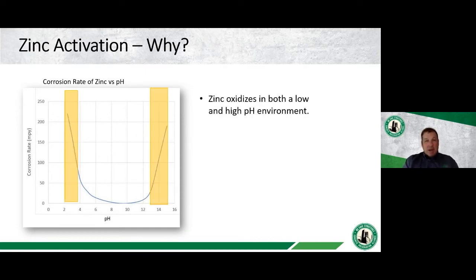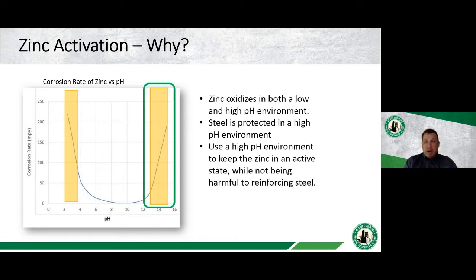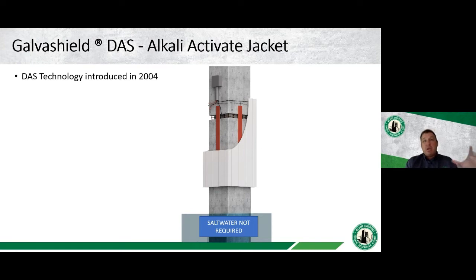So zinc oxidizes, as I mentioned, in both a low and a high pH environment. A high pH environment is actually beneficial to reinforcing steel. So we're going to rely on a high pH or high alkalinity environment, because this high alkaline environment oxidizes the zinc, or keeps the zinc actively corroding. So we can get a good corrosion rate, or a higher current output, by utilizing this high pH environment. This technology was actually introduced in 2004, so it's been in use for almost 20 years.